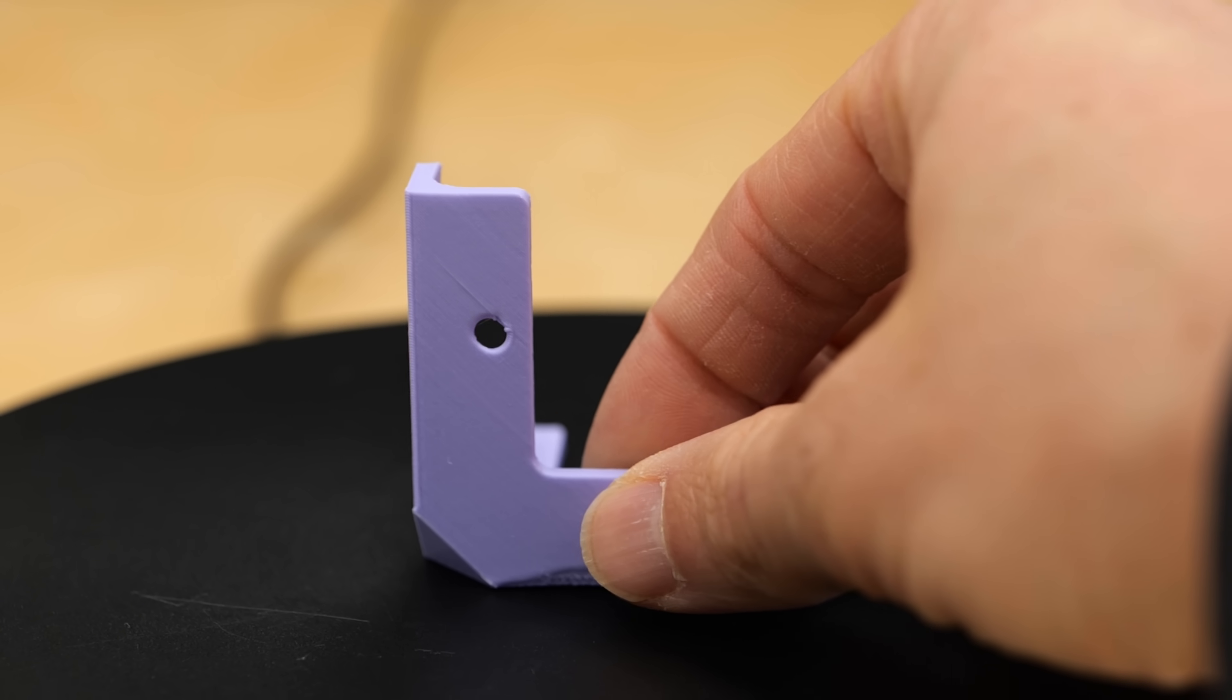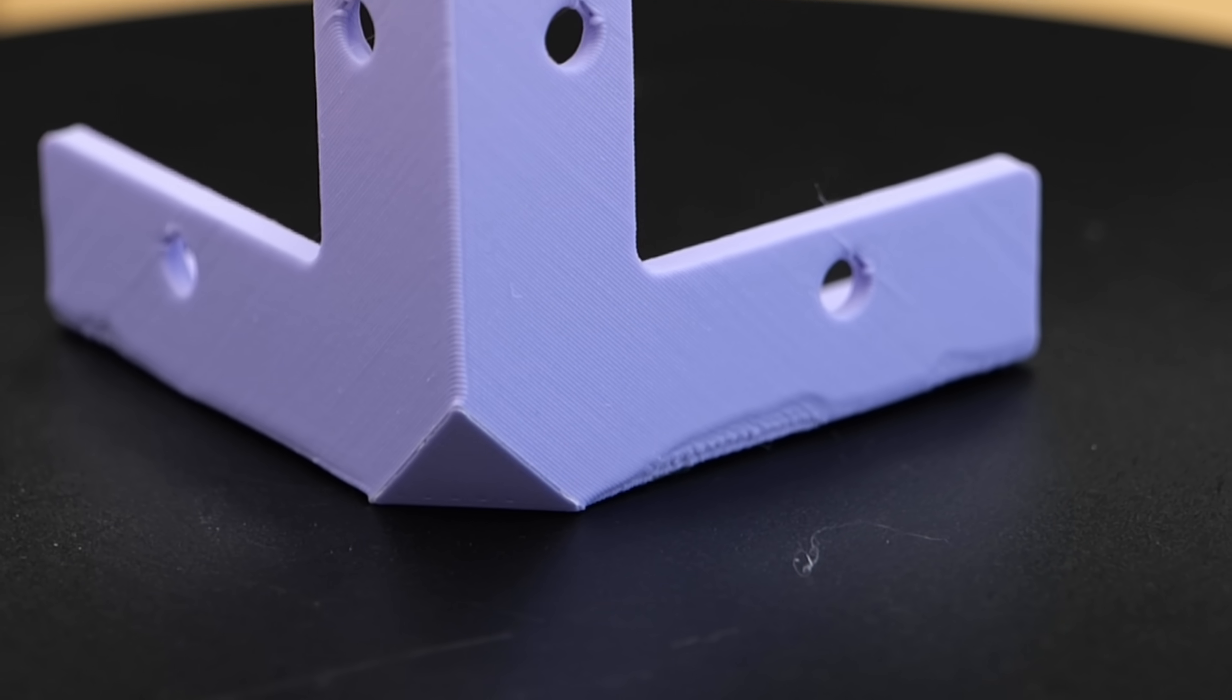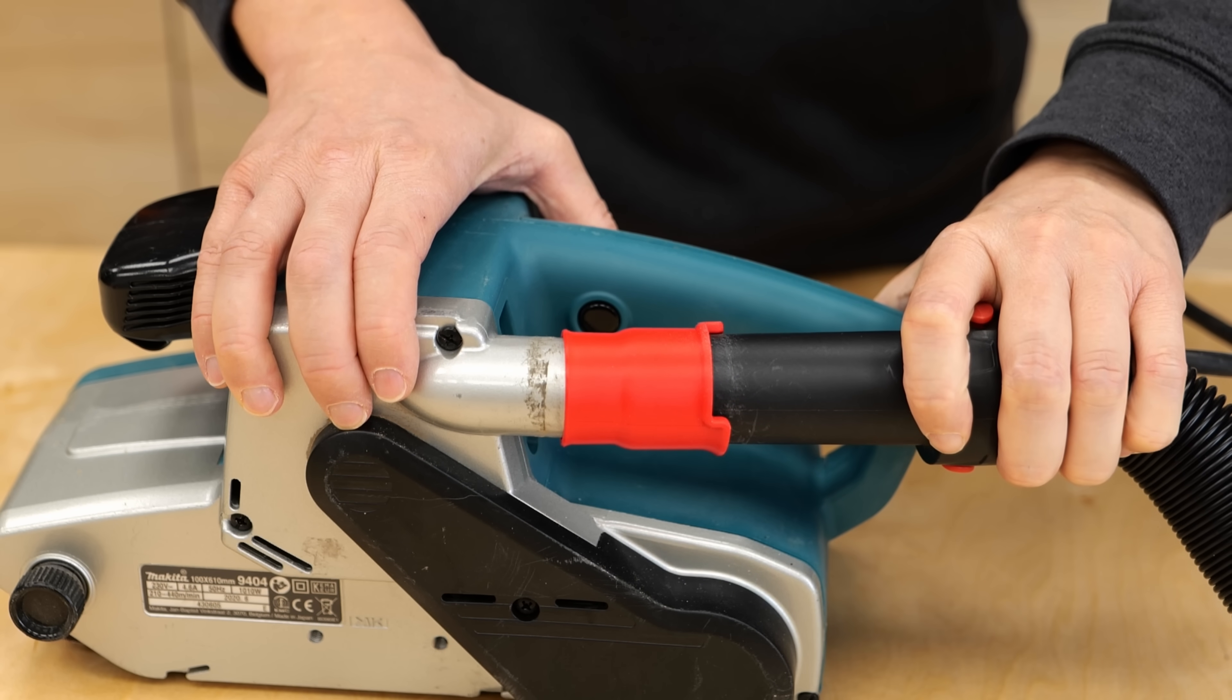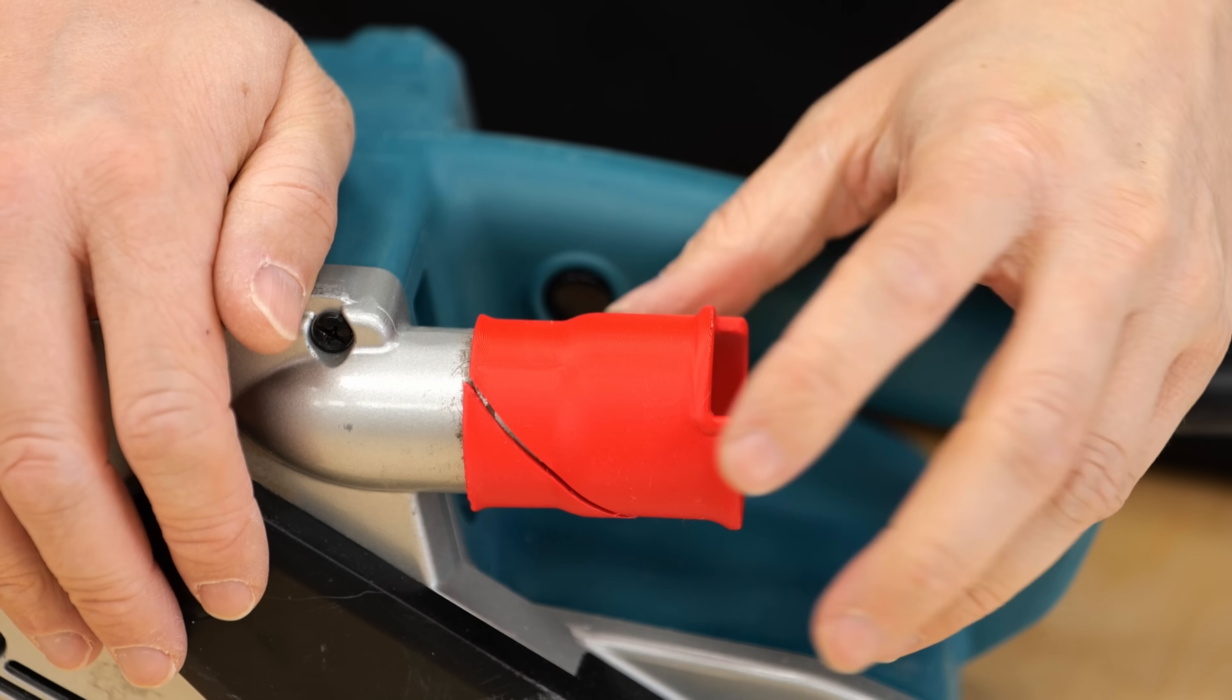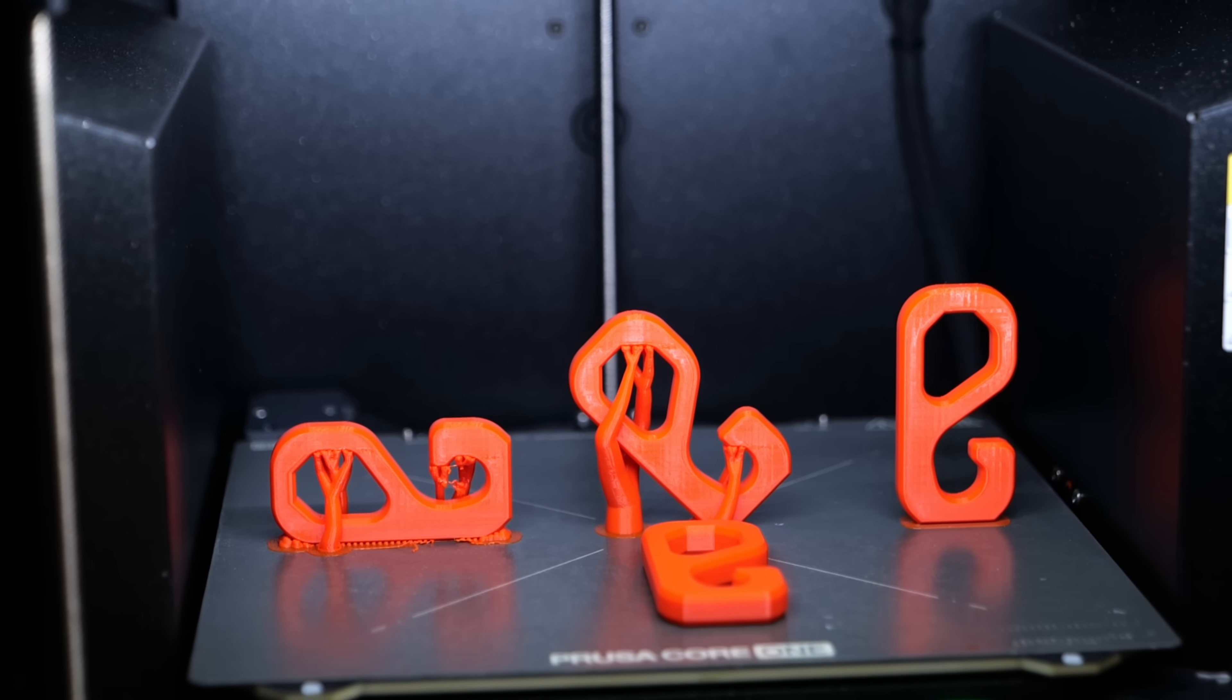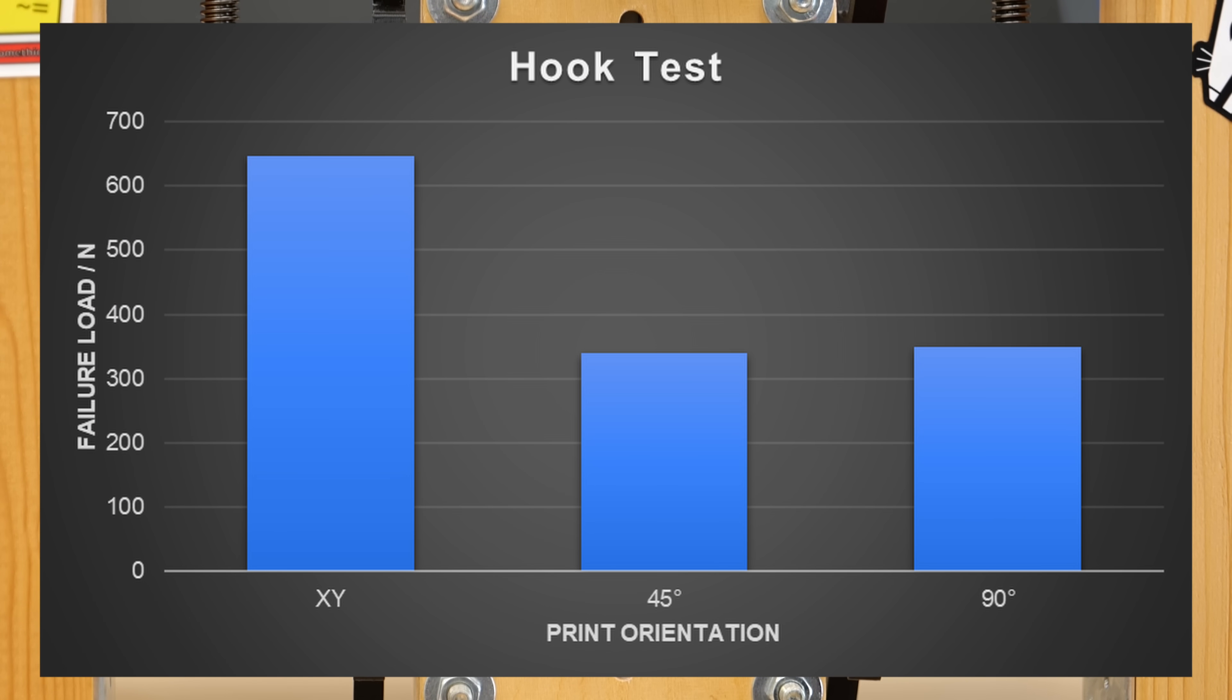But I also want to be completely transparent here. Sometimes changing the orientation can make things worse, and this already starts with the quality of the corner bracket when at this angle, the overhangs can curl up a little. You can also shift problems. Initially, my vacuum hose adapter broke during use, but when I first printed it at an angle, it split at 45 degrees during installation because it was too tight. Still, after reprinting that, it was super strong during use. Similarly, my test hook that I printed at an angle did not hold up more load than the one printed standing. And the point of failure just changed because loading itself is complex.